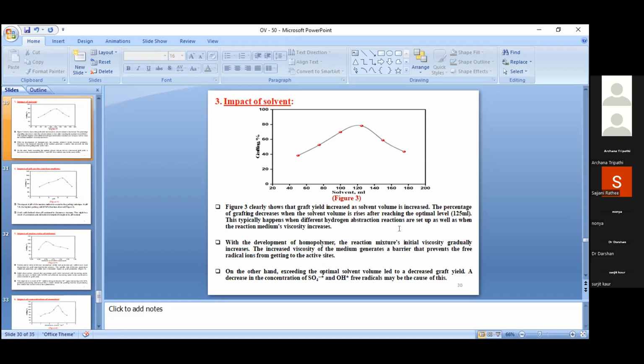With the development of homopolymer, the reaction mixture's initial viscosity gradually increases. The increased viscosity of the medium generates a barrier that prevents the free radical ions from getting to the active site. On the other hand, exceeding the optimal solvent volume led to decreased graft yield. A decrease in concentration of SO4 and OH free radicals may be the cause of this.